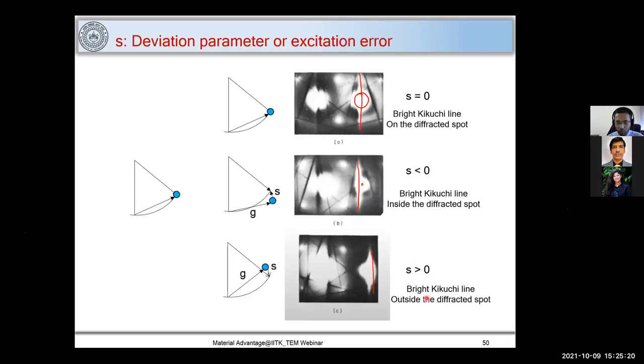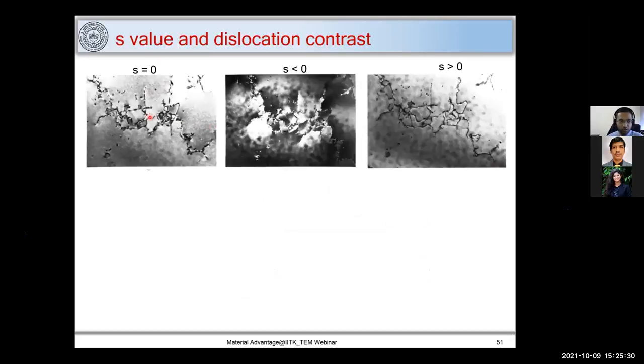So we are already in two beam conditions in this case, and we are using this S value to image dislocations. When S equals 0, dislocations are visible, but they are not clear. In this case, the dislocations are not visible at all because we go very close to a Bragg condition and the matrix starts diffracting, and thus S is less than 0, and we cannot image the dislocations. Here in this case, S is greater than 0, and you can clearly identify dislocations.